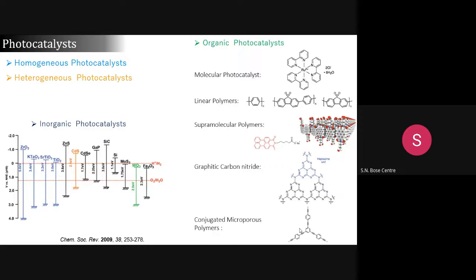And also, inorganic semiconductor has one typical drawback, that you cannot change this band gap much, like organic material. In organic material, suppose you take this system, you put another benzene, you can tune the band gap. But in this case, you can tune the band gap, but not to a very great extent. Due to this kind of tailor-made synthesis and properties, the organic material got very much attention from the 1980s.